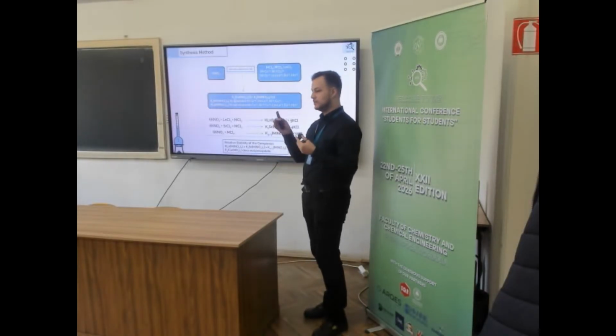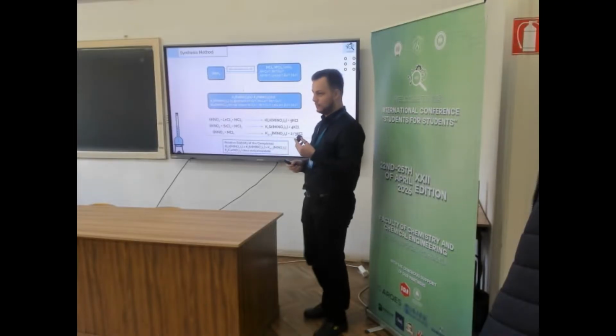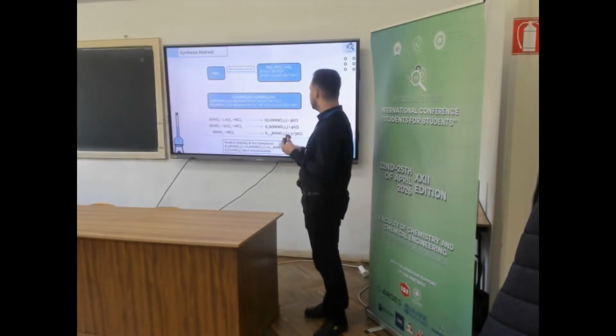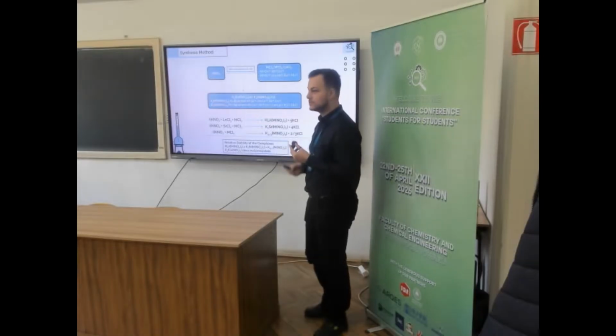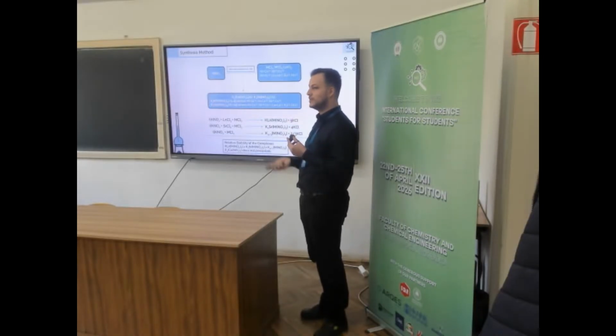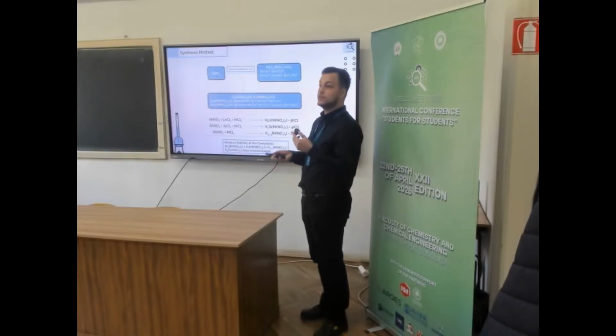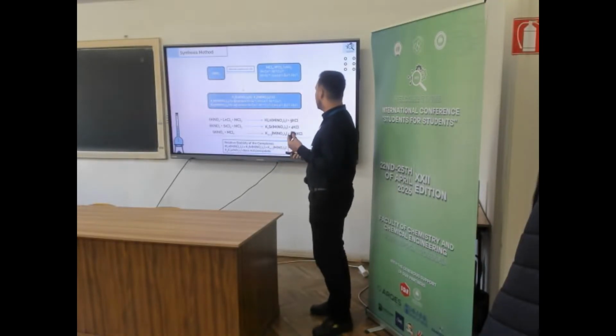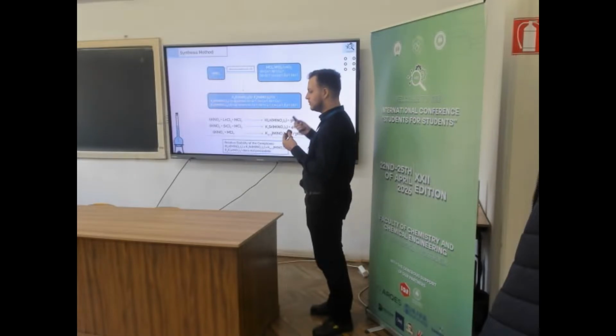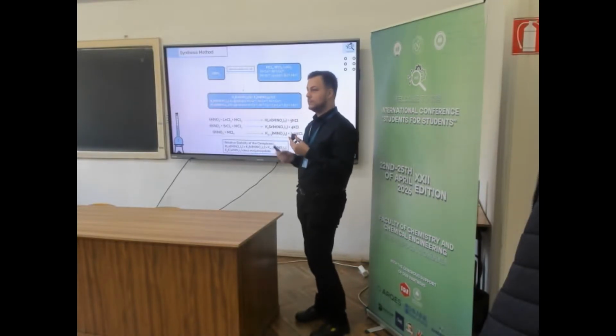Now, it can be just the chloride of the transition metal, or a mix of chloride salts, one with the transition metal and the other containing a counterion which we wanted to implement in the compounds. The counterions can be strontium, lanthanum, holmium, and europium. And these two solutions were mixed.